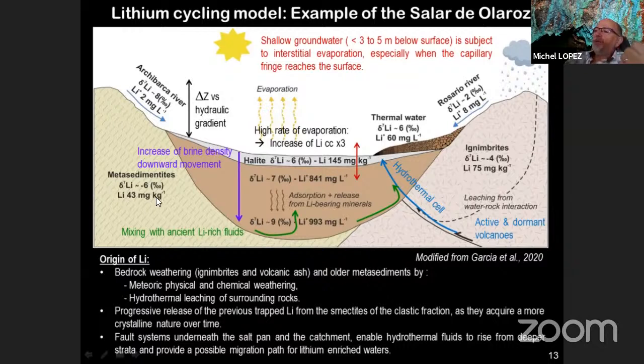So bedrock weathering is the main source of the lithium, in particular volcanics and metasediment. Hydrothermal leaching of surrounding rocks is the second process, mobilizing the lithium from the watershed, from the drainage basin. Then there is a progressive release of the lithium, which is trapped with the clay deposited in the deeper part of the system, and the fault control, in particular the hydrothermal fault, the bordering fault, because these basins are often bordered by faults. These faults correspond to the pathway for the fluid to reach the surface.